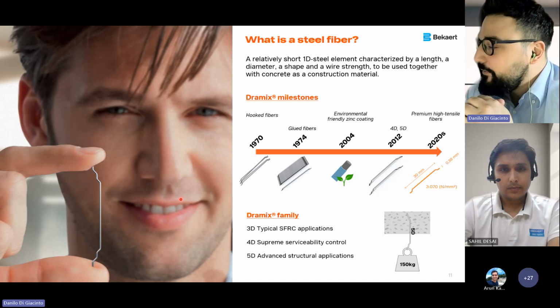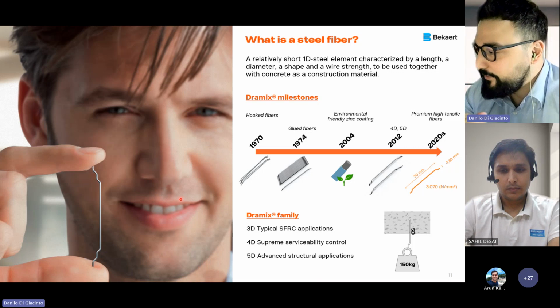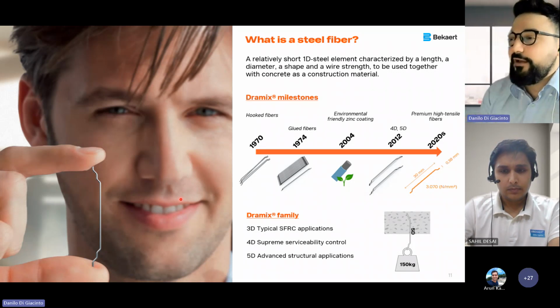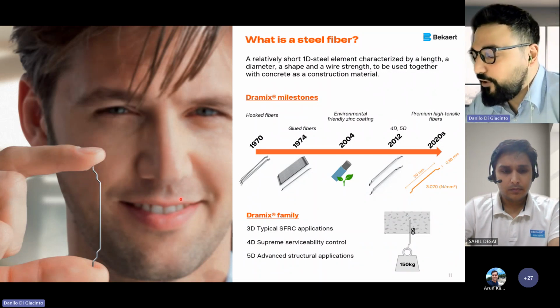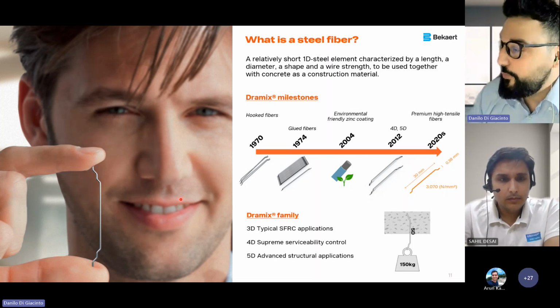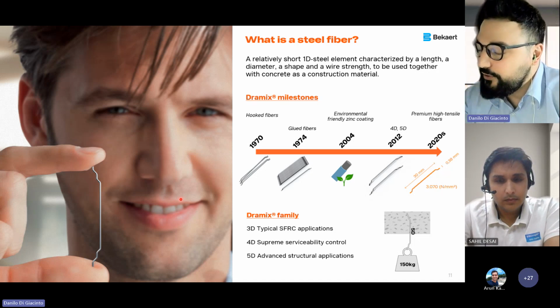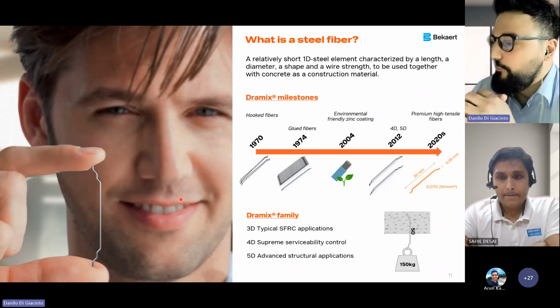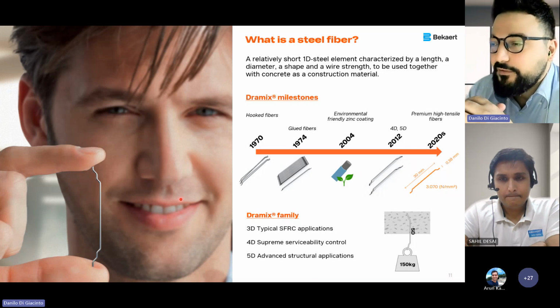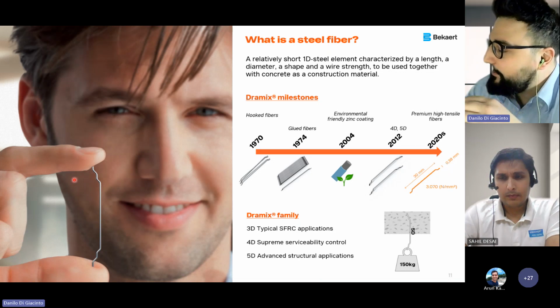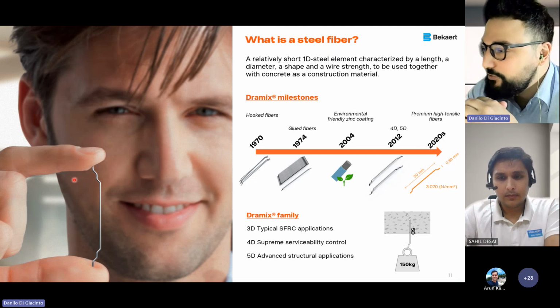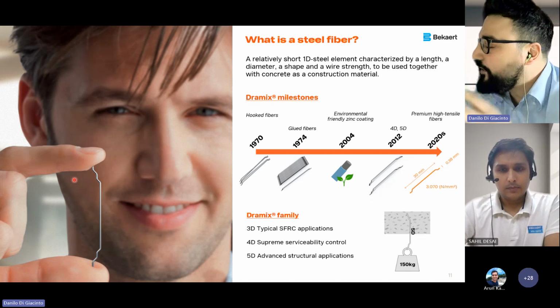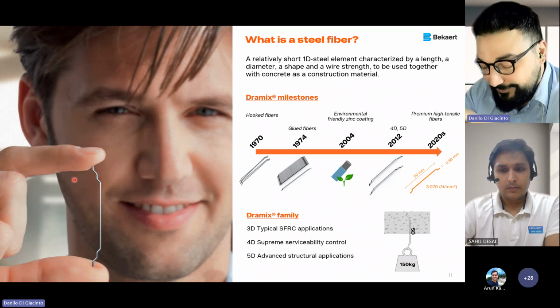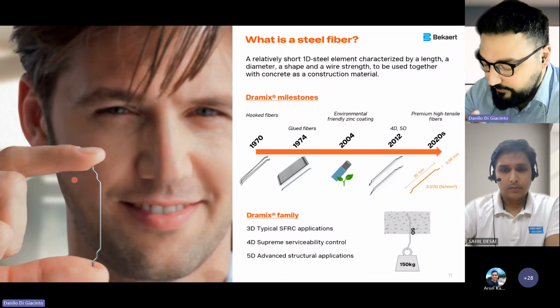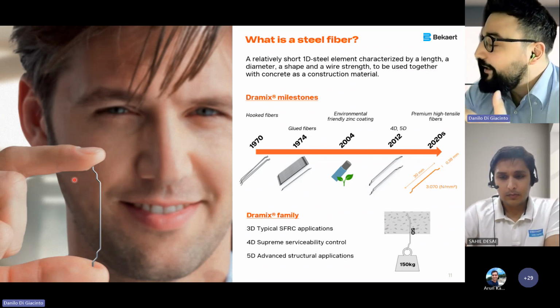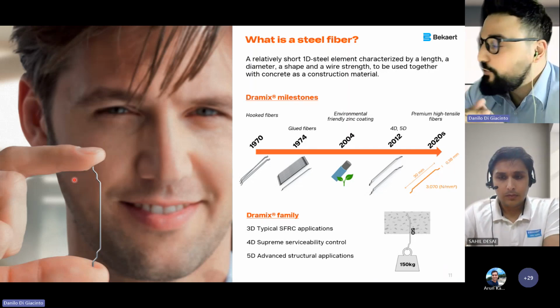A little bit about the Dramix family. We divided the steel fibers in three categories: 3D for typical SFRC application, so, for example, flooring in either fiber only or combined solution. 4D family with an advanced hook system with two bends at the end of the fiber, in which we can achieve a supreme serviceability control. And lastly, the 5D fibers with advanced structural application, a very advanced anchoring system. Just to give you an indication, with a single 5D fiber, thanks to the wire strength, which is the main improvement of this fiber type, together with the advanced hook, we can achieve to withstand a weight of 150 kg.